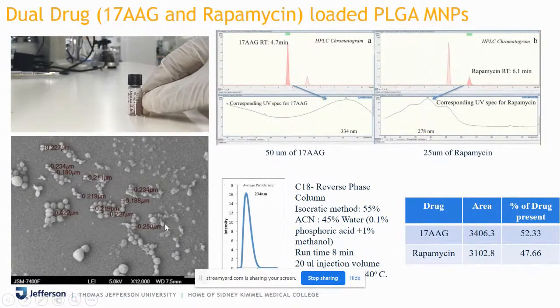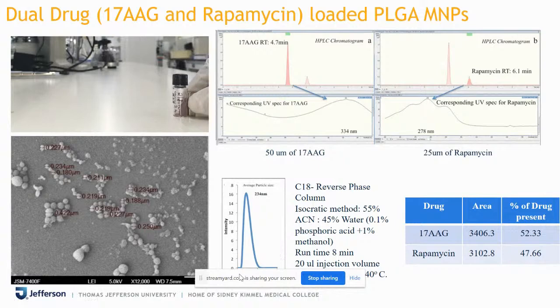The SEM images confirm the size of these nanoparticles. The particle size distribution ranged from 0 to 500 nanometers. You can see the percentage of drug present was approximately 50%, which was confirmed using HPLC. So this work is still under development, and we are still working on this part. But this experimental design gave us an idea that we could actually co-encapsulate three components in a PLGA polymeric system. After having substantial experience with PLGA, we went to another system.